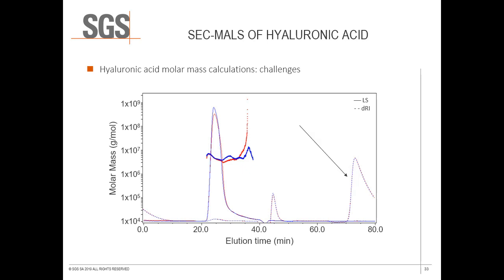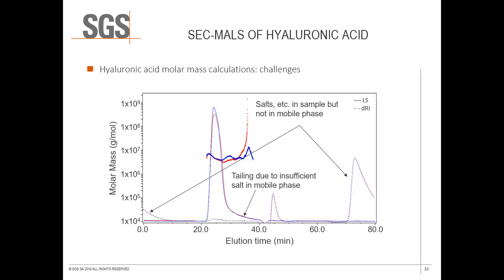The large refractive index peak seen at the end of the chromatogram, which is extended to 80 minutes to minimize its effect, and also seen at the beginning of the chromatogram tailing off from the previous injection, is due to the apparently extreme difference between the mobile phase composition and the injection solvent, which was the diluent the sample was supplied in. This, combined with the low refractive index response due to low concentration, and tailing light scattering response possibly due to an improper salt composition in the injection solvent, serve as an example of the lower quality of data that may be created due to the challenges posed by hyaluronic acid samples.